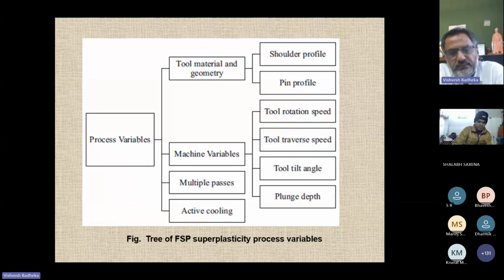But here, there is a term called active cooling. So active cooling will help you to reduce the grain size, right? Instead of achieving the higher peak temperature, with the active cooling during the FSP. I mean, you can do cooling with a variety of sources. Researchers have done it with even liquid nitrogen also. Researchers have tried with compressed air, even with CO2, and maybe with submerged cooling as well. So these active cooling methods will help you to reduce the grain size and may help you to achieve a better